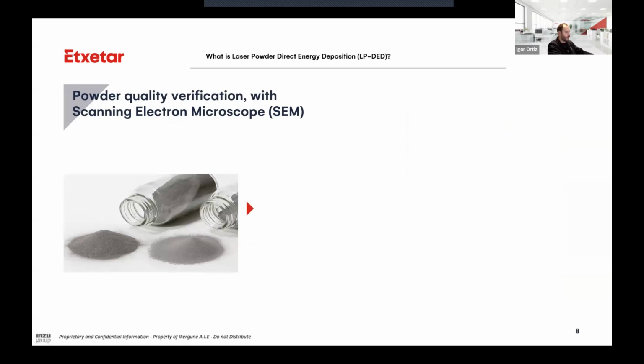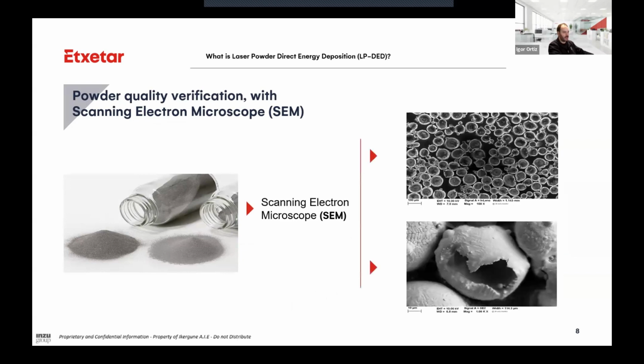We do a lot of research in powder quality characterization. We look at different suppliers of powder, and we check each supplier and each powder if it's a new supplier. We want to avoid porosity in the powder, because in some materials like Inconel 718, this porosity is reflected in the tracks, and even if we have good process parameters, the tracks and the part have porosity, so the part is not suitable for entering service.